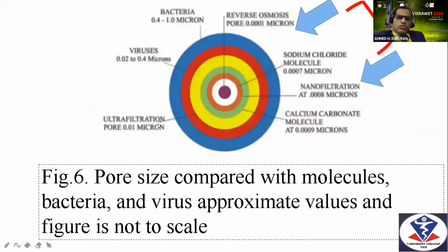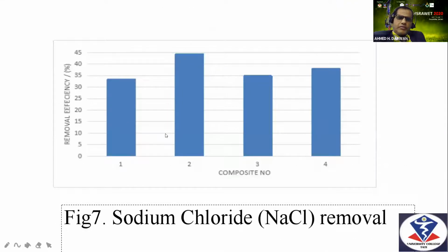When we study the porosity of the membrane, oh, you cannot see very clearly here. This is reverse osmosis, okay? And here we have nanofiltration. So between them is sodium chloride removal. If you have porosity smaller than nanofiltration, it can remove sodium chloride. If it is higher than nanofiltration, 0.0008 micron, then it cannot remove it, it means that it will pass. After analysis, we got about 45% removal efficiency of sodium chloride by the ceramic membrane we fabricated in TATI UC, or UC TATI.